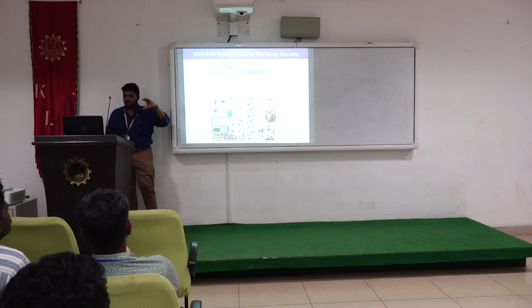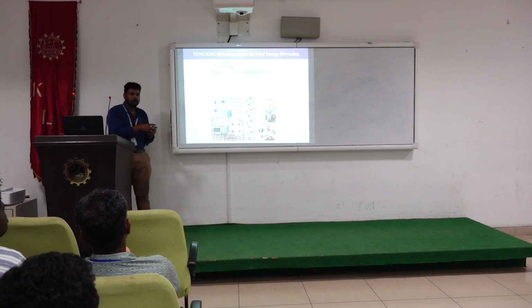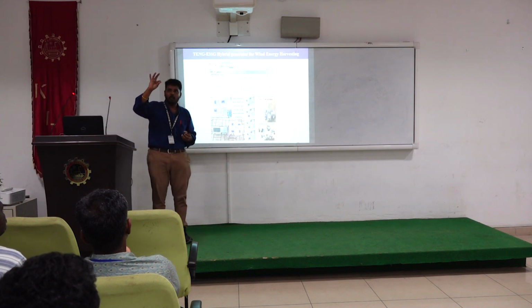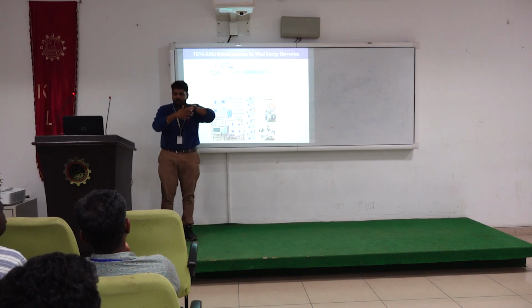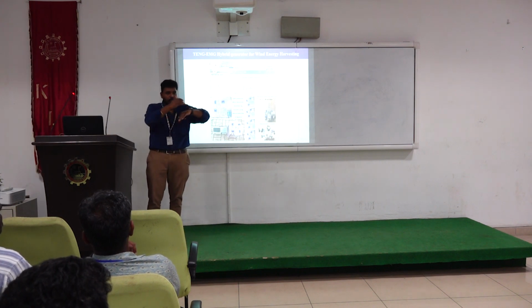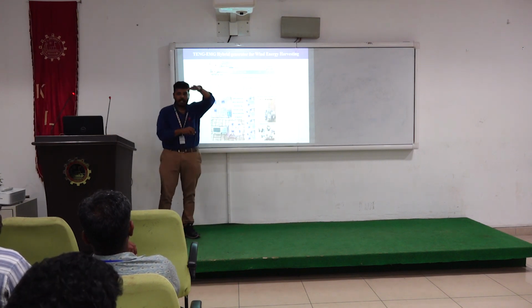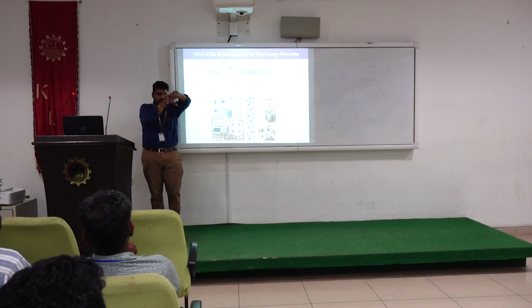In the small wind tunnel, we have a thin Kapton film. If I hold this Kapton film like this, in wind it will start to flutter. On this Kapton film, I used inductively coupled plasma etching to etch one side to create more roughness. On the other side I put aluminum. When it flutters in wind, it creates friction.